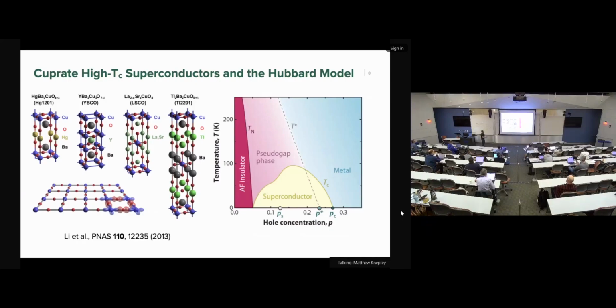The right-hand side is a common phase diagram for these materials, as a function of temperature and doping hole concentration. On average, without doping, you have one hole carrier per copper-oxygen plaquette, and you can introduce more hole carriers through doping. Without doping, the material is actually an antiferromagnetic insulator, with checkerboard spin arrangements. This state cannot be explained by, for example, standard first-principles calculations or density functional theory. That's why we need more advanced calculations that we will introduce shortly. And if you introduce more hole carriers, then the system can become superconducting.